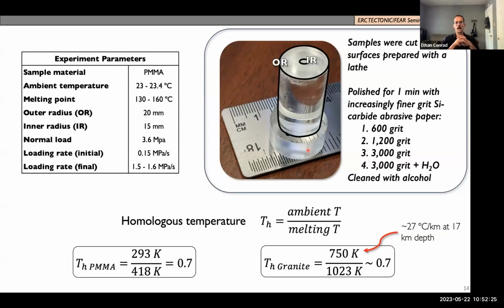So here's our actual sample. It's two pieces, and I drew an outline just to show those two pieces more clearly. We have our upper cylinder, which is slightly thinner than the lower cylinder. And the upper cylinder has an inner hole that's drilled so we can thread a thermocouple in, and then an outer radius, and that outer radius is about 20 millimeters.